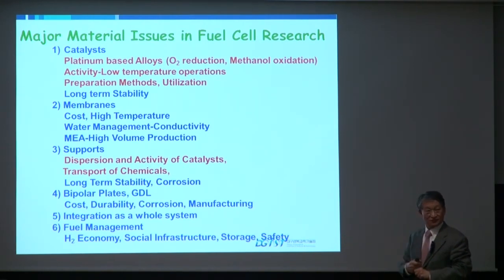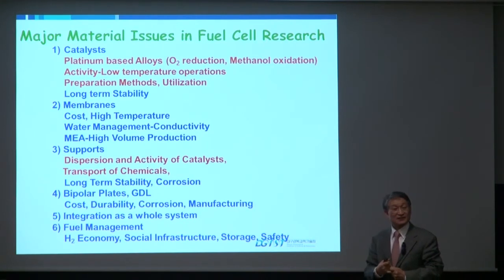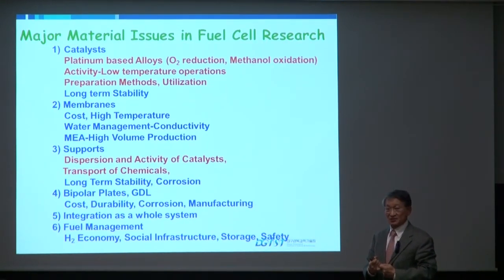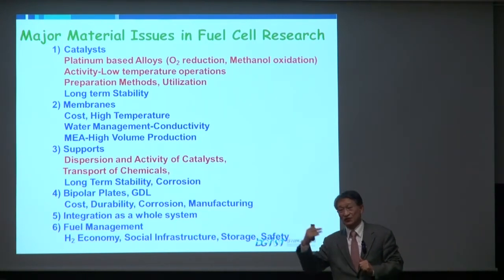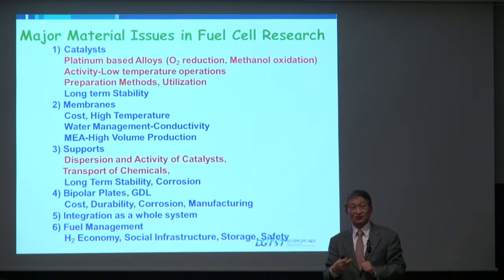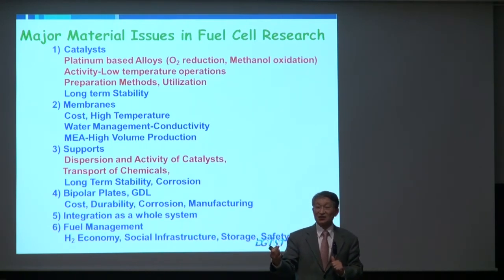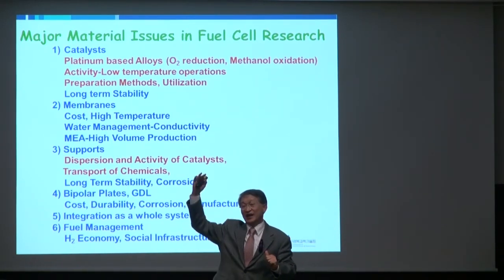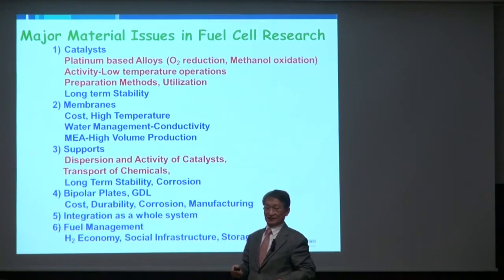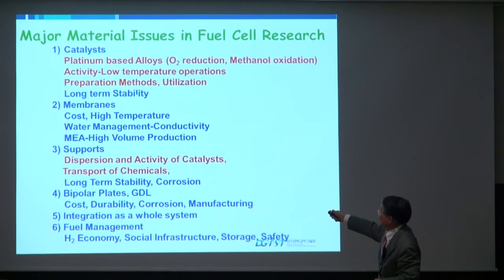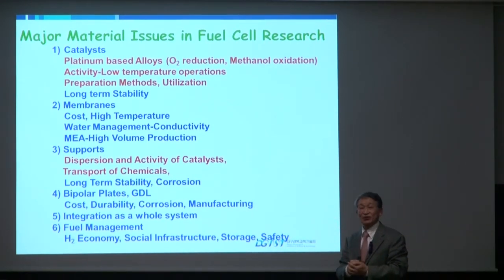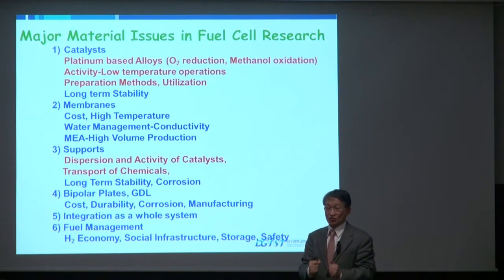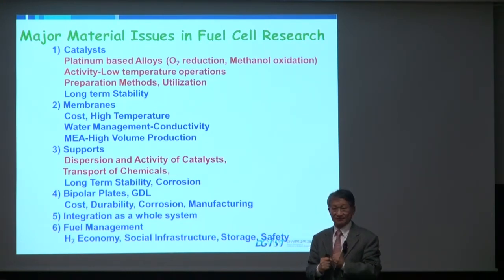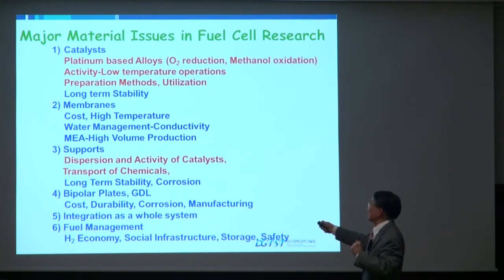Low temperature operations. The PEM operates under 100 degrees. So catalytic activity is pretty low compared to solid oxide fuel cell, which operates at more than 650 degrees. In solid oxide fuel cell, you don't need to worry too much about the catalyst itself because the temperature is very high, the activity is very fast. Then long-term stability. Long-term stability or durability is another big issue in fuel cell applications. So many people are working on this part.